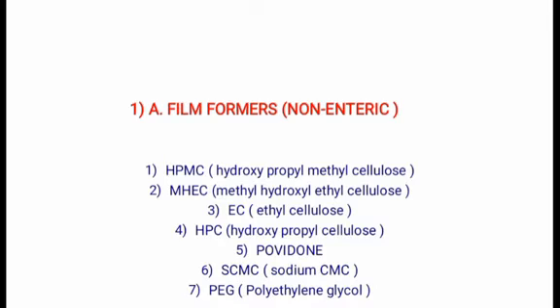The third one is EC, that is Ethyl Cellulose. It is manufactured by the reaction of ethyl chloride with cellulose dissolved in NaOH. It is water insoluble and thus cannot be used alone for tablet coating. It is usually combined with water-soluble additives, for example HPMC, to prepare a film with reduced water-soluble properties.